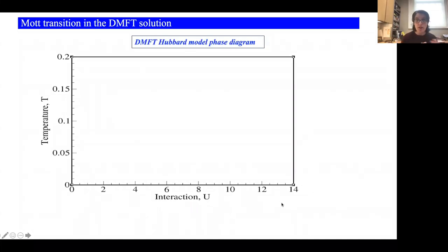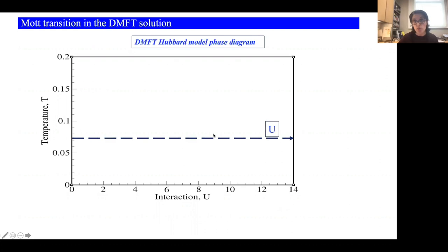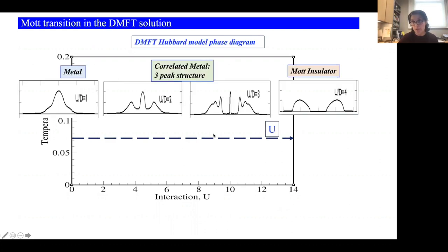So in the Hubbard model, the metal-insulator transition can be driven either by temperature or interaction strength U, or in experiment, it's equivalent to changing the pressure in the system. So if you fix the temperature and change U and plot the density of states obtained using dynamical mean field theory, you will see that the density of states changes from metal to correlated metal with this characteristic three-peak structure, and to the Mott insulator characterized by the gap opening in the density of states.